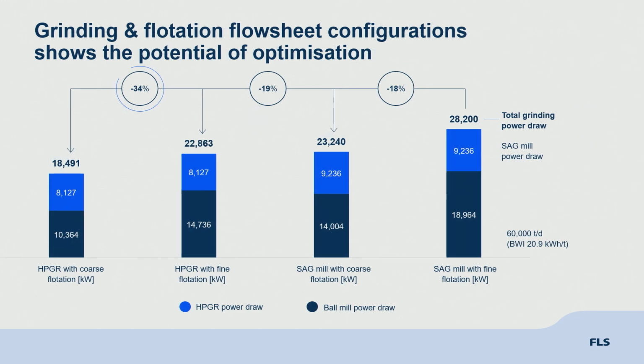So then we dug in a little bit deeper, knowing that there are mines out there that maybe want to do brownfield upgrades and won't have a full greenfield, so they can't start the mine planning from the beginning. So we looked at a conventional SAG ball circuit with fine grinding. And when I'm referring to fine grinding, it's not that fine. It's 150 that I'm referring to here. And then we changed that with coarse flotation and using the SAG ball circuit. And we managed to reduce the energy by 18%.